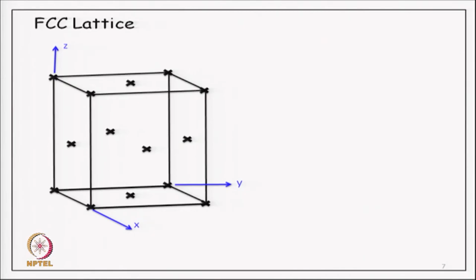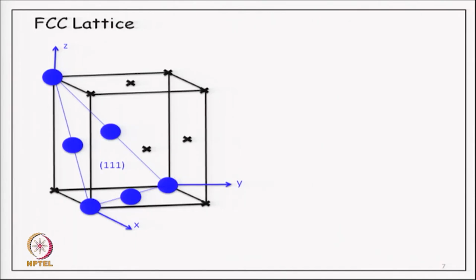at one step, or a step of a, that is along the corners here. So, this is my 1-1-1 plane identified here with these thin lines. Now, in a first step, I place atoms only on this plane, one at each lattice point. So, I begin with that corner, then I place one on this face center and another corner atom, bottom face center, then that corner there, then back face center. So, these are the 6 atoms which are lying on this 1-1-1 plane within the unit cell.